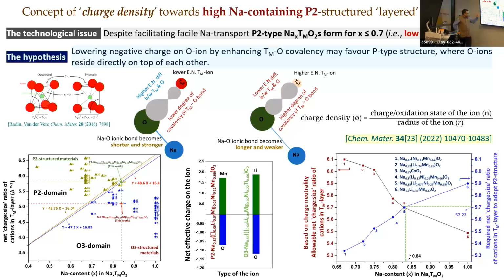So one can know that, okay, if I want a sodium content of this, say 0.9, I need to have a charge to size ratio of 6 or more to be on this side of the line. If I have it lower than that, I will be lying on the O3 domain. So based on this, we designed two compositions, one with the charge to size ratio falling in this domain, and the other with the charge to size ratio falling in the O3 domain.